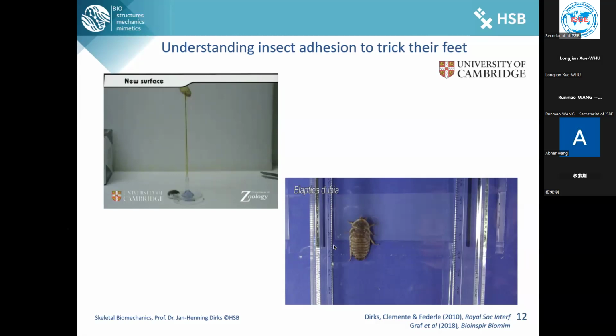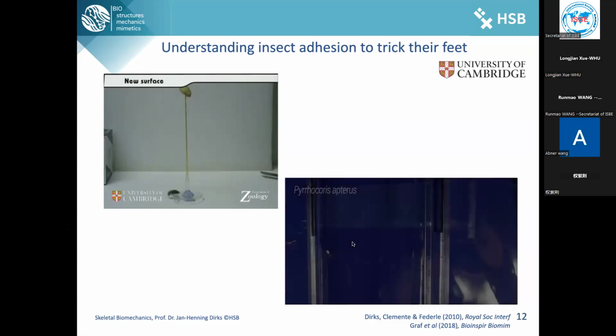But there's like a death zone of roughness that is too rough to use the adhesive organs, and not rough enough in some way to properly use the claws. And if you can design a surface that is exactly in this range of roughness, then we developed a method basically to test this.